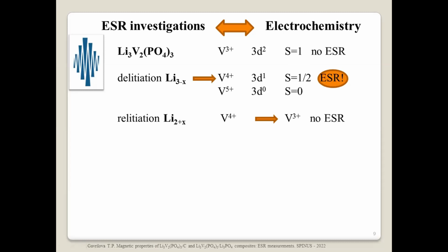During the charge of the electrochemical cell, which means delithiation of this cathode material, lithium ions should be removed from the structure. And to preserve electroneutrality, vanadium ions can change their valence state from 3+ to 4+. In this case, they have spin 1/2, and we should observe a very good ESR signal.